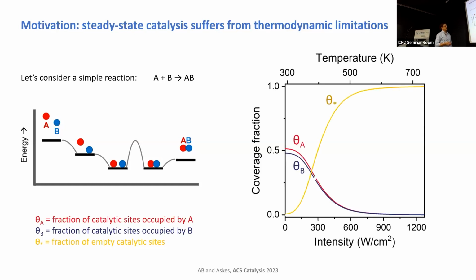Now, what happens at different temperatures? Here I'm plotting the coverage fraction theta A, theta B, and theta star as a function of temperature, or if you are in CW, so continuous wave irradiation, as a function of laser intensity. Essentially, how hot are we making the catalyst? Now, if A and B have similar adsorption property on the catalyst, essentially at room temperature or at cold temperature, the catalyst will be populated by A and B 50-50. So the whole surface is covered. And the percentage or the fraction of free sites will be 0.